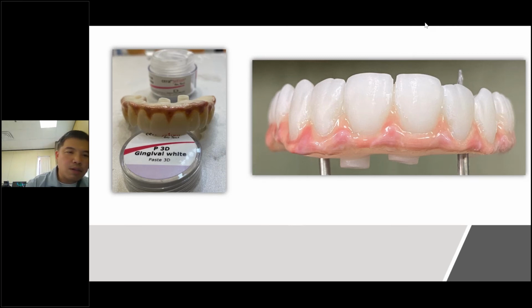So all we gotta do is make sure our pinning is done correctly. Now, the biggest part about firing porcelain on zirconia hybrids like this is that we need to make sure we control our temperature. Even though other companies will tell you that your firing cycle for your pink porcelain is only 15 or 18 minutes, we have to extend our firing cycle to 2 to 3 hours.